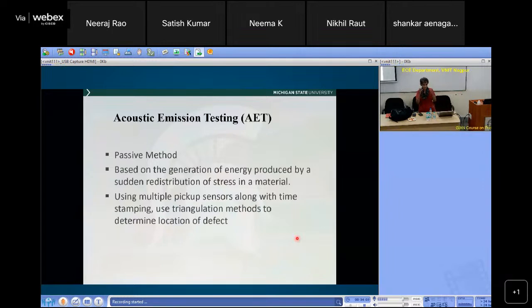There is, at the crystal structure of the material, if there's a dislocation in the very, very initial stages of stress, there is a release of energy from somewhere, and it will travel to the surface because it is sound, but it is at the acoustic frequencies, much lower frequency sound, and you can pick that up. There's no incident energy. It's created by itself.